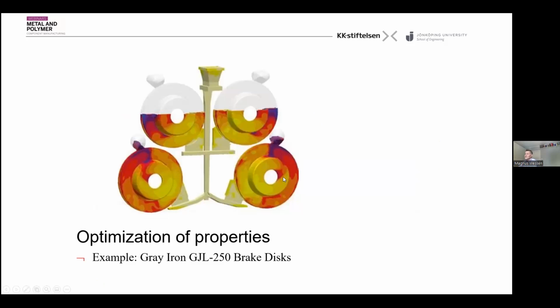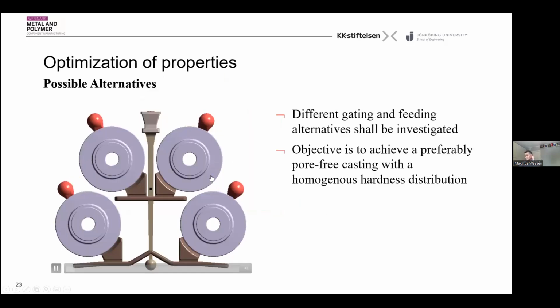Another case which is fun combines a little bit of porosity and the mechanical properties. This is brake discs, and how you orient your brake discs in relation to your gating system and your feeders, you will have variation in properties. The feeders will cool the part more slowly during the microstructural transformation. That means you have lower strength.